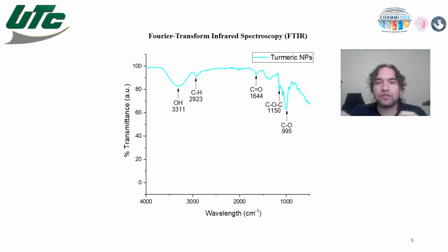Okay, now we have the spectrum corresponding to the turmeric nanoparticles. First, a band at 3311 was observed, attributed to the vibration of hydroxyl groups, indicating the presence of bonds related to the surface functionalization of the nanoparticles. Additionally, a signal at 2923 was recorded, characteristic of aliphatic stretching vibrations, which reinforces the presence of organic components in the structure. The signals at 1150 and 995 are attributed to the vibrations of carbon-oxygen-carbon and carbon-oxygen bonds, respectively, representing the interaction present in the curcuminoid compound. Finally, a band at 1644 was identified, corresponding to a vibration of the carbonyl group, a key signal related to the chemical structure of curcumin at the nanometric scale, in accordance with what has been reported by different investigations.